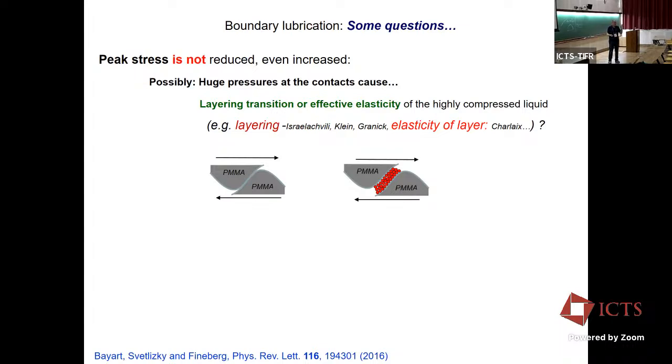Not only water, anything, many liquids. And you can have various models giving elasticity to these layers, but basically we're filling in the little nano voids here. So we're increasing the contact area actually, and giving higher strength to this contact. And so the residual strength is lower because once these get past each other, then the lubricant actually starts to lubricate. It reduces the friction.